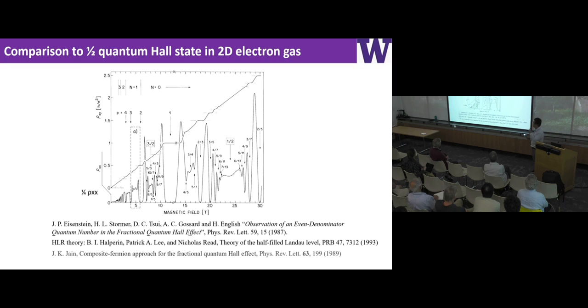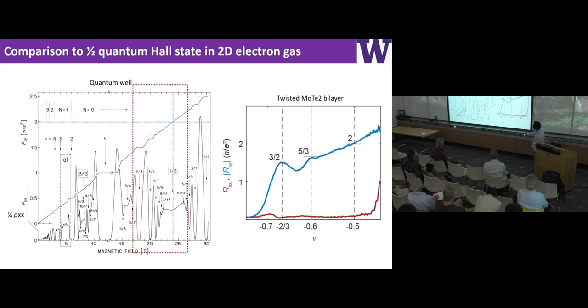So what's going on? Well, I don't know, but I'm an experimentalist. I'm superficially comparing to what has already been done in the past for 2D electron gas systems. This beautiful data, much cleaner than what I show you, is what you get if you focus on the 1/2 filling as a function of magnetic field. You will see this Rxy is about 2h/e squared. Now, if I look at these data from the 2D electron gas first, as I tune the magnetic field, equivalent to the filling factor, you see the first bump, the 2/3 state, second bump, the 3/5 state, some little bumps, then linearly increasing. Okay, this really looks similar to what I have here: one bump, second bump, then linear increase. So there could be some kind of intrinsic connection between these two phenomena.